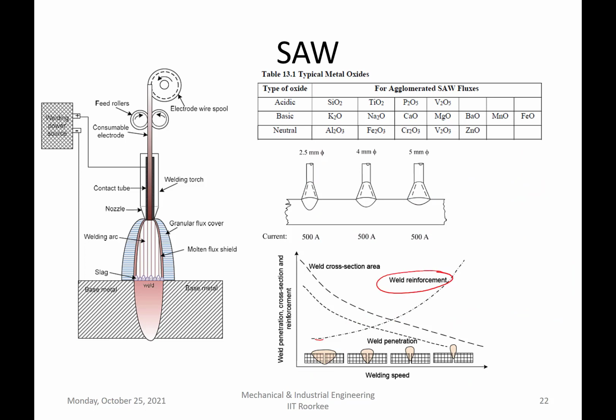Reinforcement is increasing with the increasing weld speed, because of the reduced heat input, reduced temperature, reduced fluidity, increased piling up of the molten metal. And this is about penetration. Penetration is also decreasing with the increase of the speed. Okay, and this is simply attributed to you reducing the amount of the heat, and the same is true for your weld cross section.